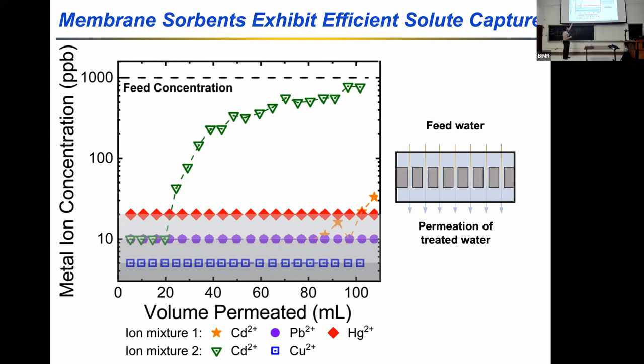But we're able to capture cadmium for a short period of time before the copper just outcompetes it. And so because the copper's outcompeting it, you can see this breakthrough of cadmium. And so it speaks to the selectivity of this functional group for copper over cadmium. And it also speaks to the rapid mass transfer and sharp breakthrough that we can get with these membrane adsorbers.